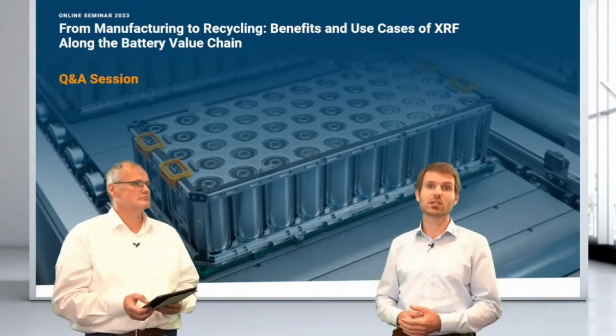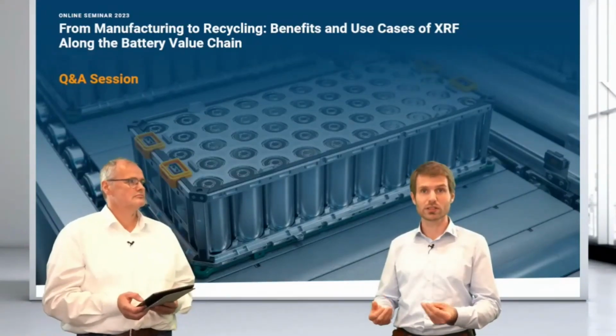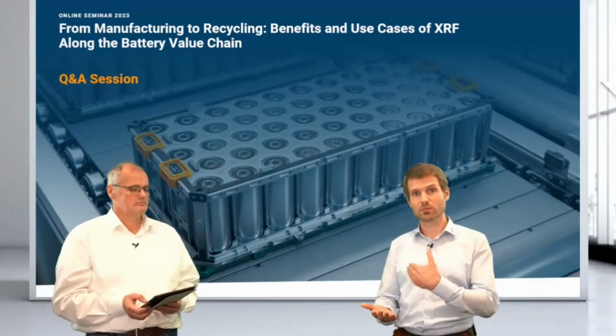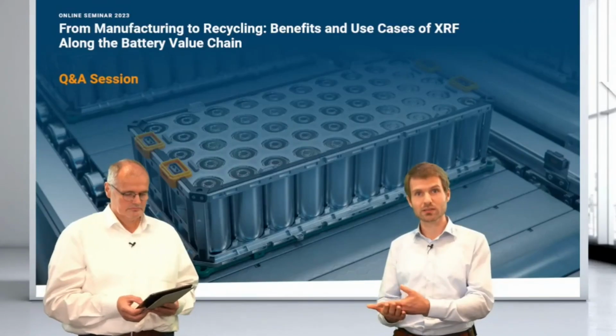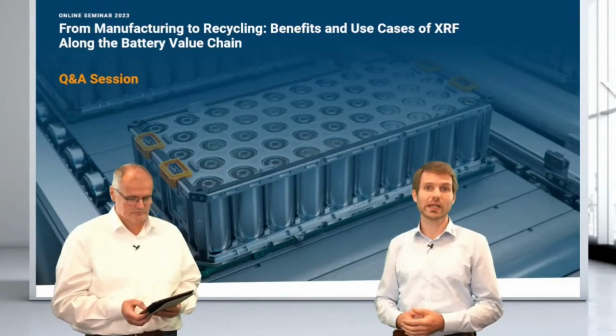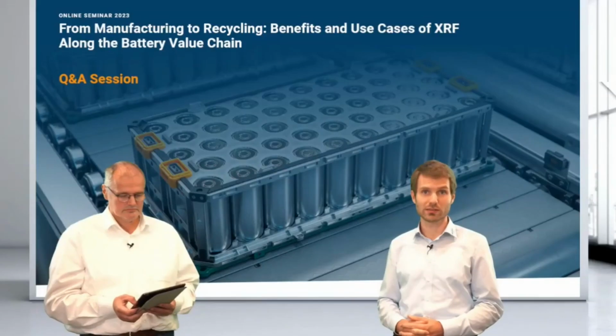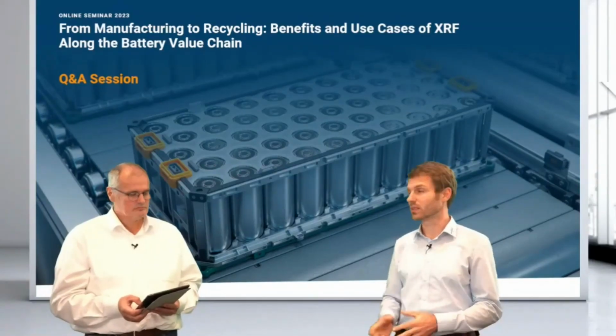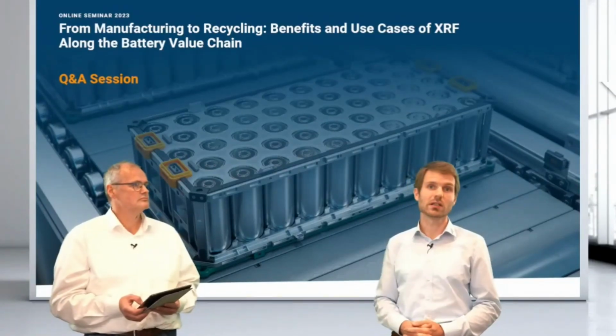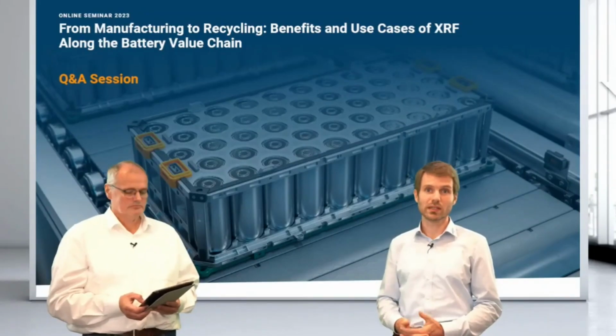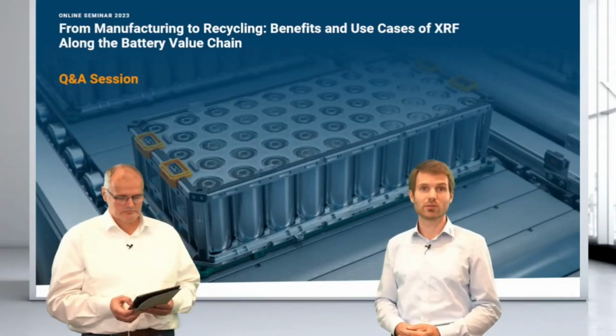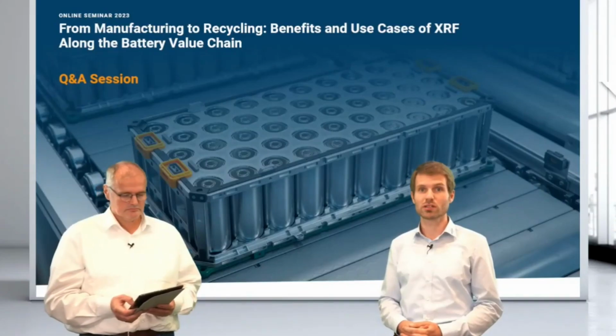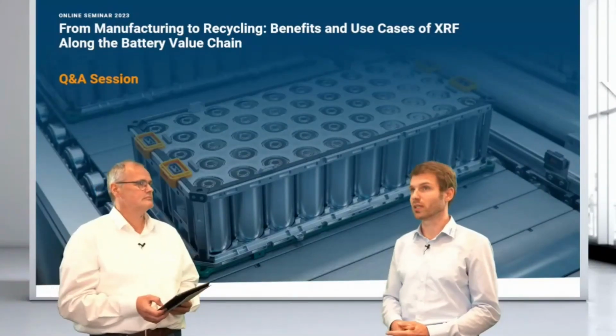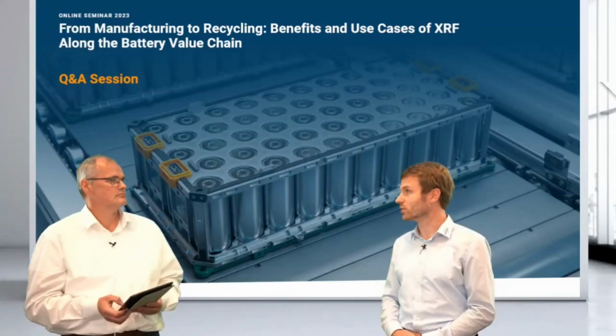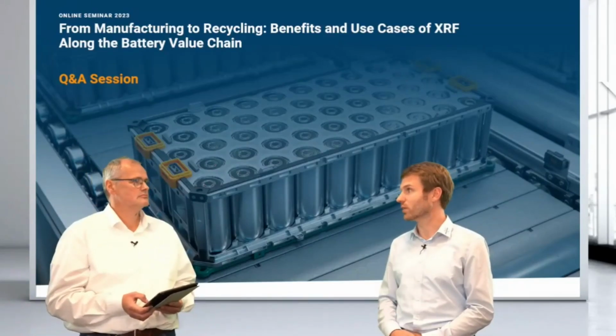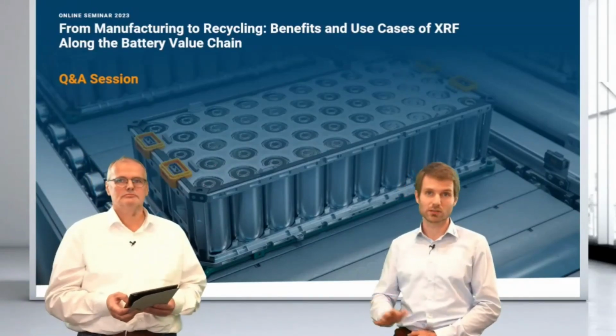If it is a material that is a bit wet or slurryish, it might be a way to put it on a substrate and dry it. Or if it's dry anyway, then you can typically press it. Maybe you have to add some binder to get a good solid pellet out of it. But then you can measure residual fluorine concentrations to, let's say, the higher hundreds of ppm or 1,000 ppm, depending a bit on the substrate.